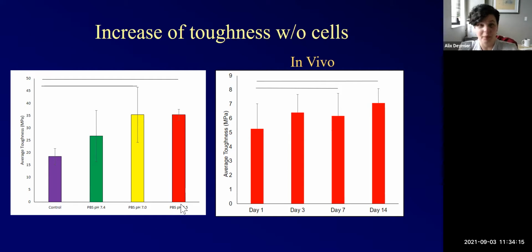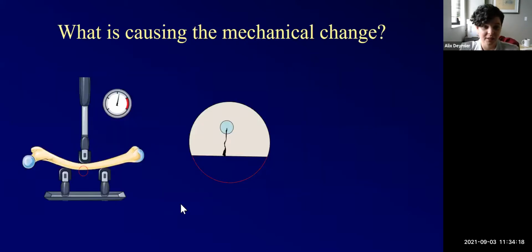Now this is a bit of a confusing thing because I had theorized that the reason that the toughness went up was that the interior was modified, that I had a decrease in mineral to matrix ratio, which made a plastic zone. But I know that in this system, the interior didn't change. I didn't have this loss of mineral to matrix ratio. So it really becomes a question of, what is happening here? Is this not what I expected?